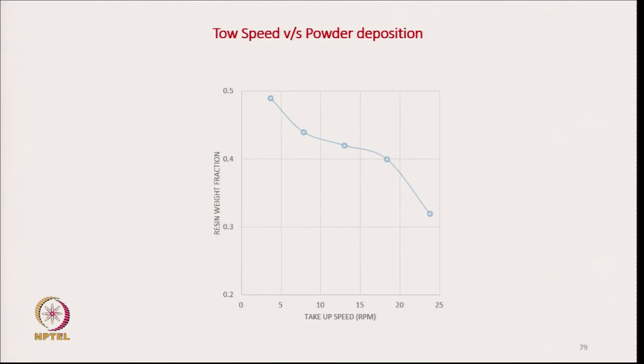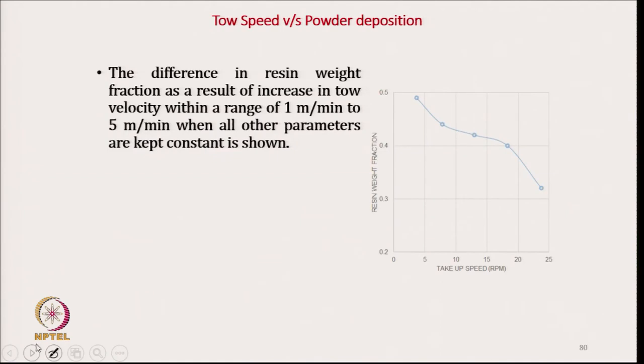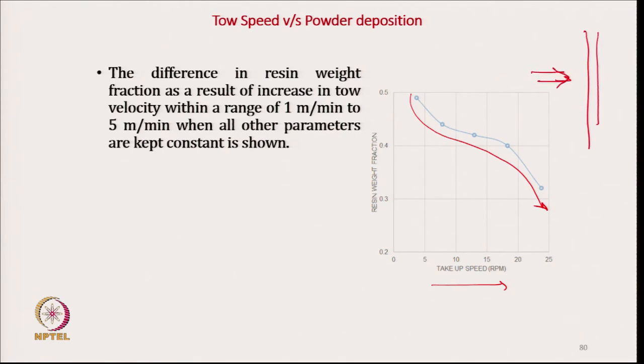Next experiment was the effect of tow speed on powder deposition. We can see that with the increase in take-up speed, the resin weight fraction consistently reduces, which can be explained by the residence time. If the residence time in the chamber is more, more and more powder will get deposited on the surface. If the residence time is less, less time will be available, so powder deposition will be less. So, it is very simple.